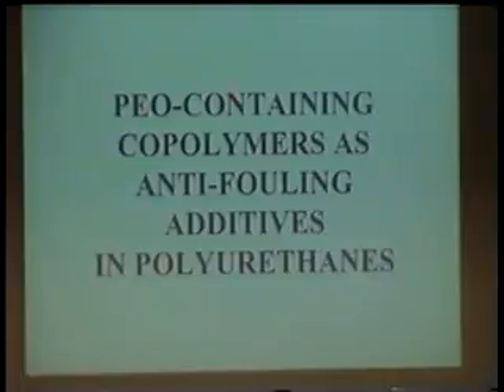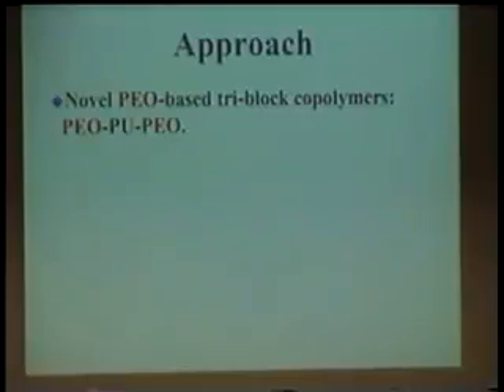And we've done a lot. We've done other systems containing PEO, but the reason I'm telling you about this one is it's the very, very best. We haven't published it, for one thing, which is always interesting in the seminar, I think. And for another, this is the best way that we have found to do this. It's the simplest and the best. So the approach is we've synthesized these polyethylene oxide-based tri-block copolymers with this structure, PEO on the ends, and the polyurethane center block.